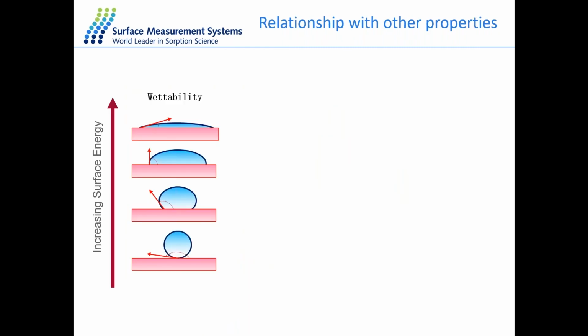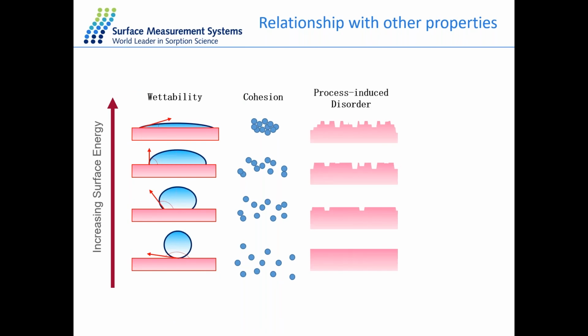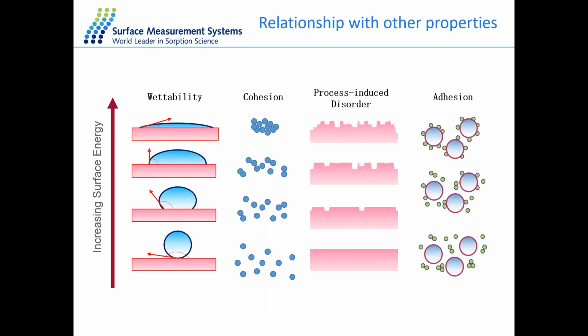Surface energy is an interesting property because it can be related to other different types of properties. With increasing surface energy, you have an increase of wettability. You also have an increase of cohesion. So this is how likely your materials are likely to interact with itself. Because we can inject multiple injections at different concentrations, we can also have a look at how homogeneous or how heterogeneous the surface of our sample is.